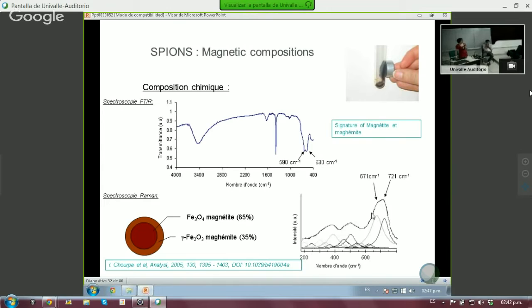And tomorrow I'll get back to this point because it's quite interesting. You cannot say X-ray in general, but the X-ray as we practice it, like X-ray diffraction, would not give you any difference. But if you go to a synchrotron, and I think there is one in Argentina or Brazil maybe, there is a technique which takes like 1 second, and it's called XANES. And this will give you, in an unambiguous way, the amount of maghemite and magnetite.